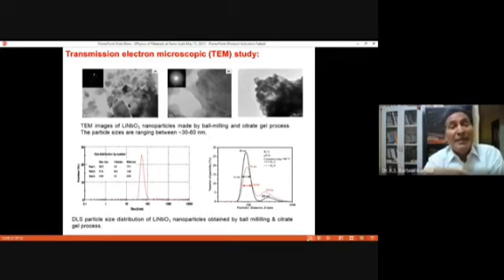It should have a single phase also, because if you have a different phase in one bulk, it will not work. In some cases it will work, in some portion it will not work. So you have to check whether it is single crystal, single phase, and certainly with the same lattice parameter in bulk from one area to another. So you have to have the transmission electron microscopy, as well as the DLS size.